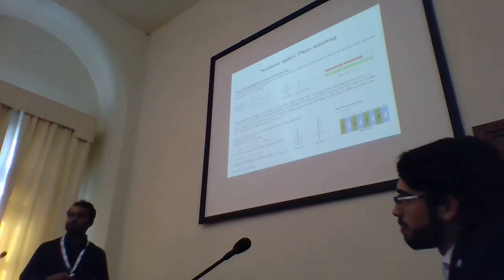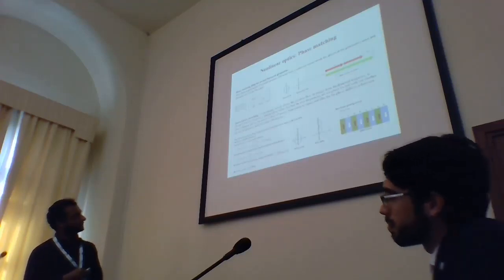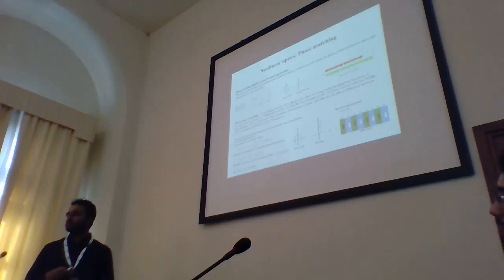In this picture, what you can see is, if you do not have a phase matching condition, your second harmonic contributions inside the crystal are quite random. These are just the phases of the complex amplitude. So most of the second harmonic field is just lost inside the crystal. But if you have a phase matching condition, the phases can be aligned, and you can have a cumulative field and output which is far better than when you don't have the phase matching condition.